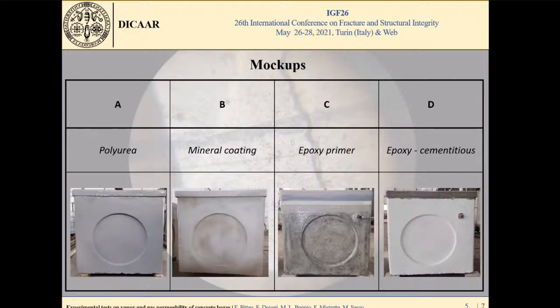The ongoing international codes admit, naturally, it's obvious, that concrete can have some cracks and so some principal path to gas, to water and other elements. But with an external coating, it's possible to ensure, of course, best performance as in the pool or other element with water. The problem is that in the pool or other condition, we have an internal coating, not an external. So in this case, there is a pressure that is unfavorable for us. And this is the real reason why we started this campaign, and the company that sold us this product highlights the main problem, that is that the pressure in this case is internal and pushes out the coating.